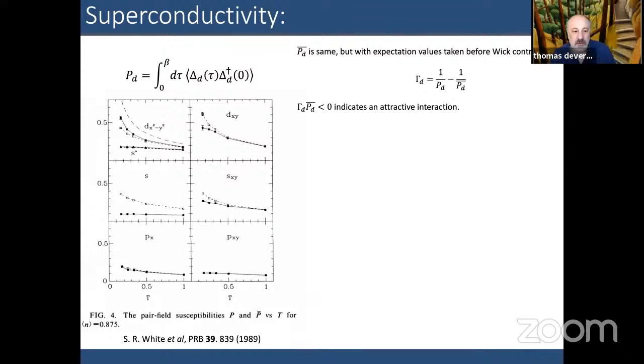Okay, so turning to superconductivity from quantum Monte Carlo, it was well known from a long time ago that in three band and in single band, the dominant pairing occurs in the dx squared minus y squared channel. And we could look at that for the pair field susceptibility, which is a time integrated delta delta dagger expectation value. So we could look at that by itself, or we could look at the superconducting vertex, which just takes away the U equal to zero piece of it.